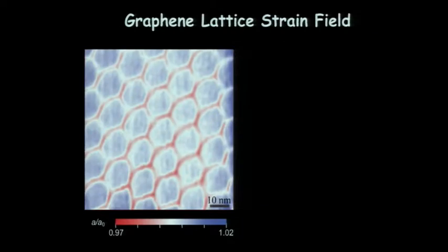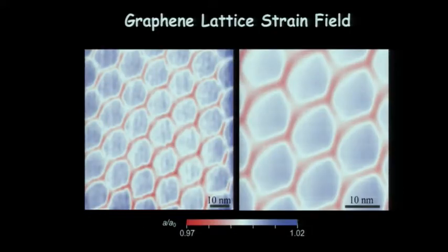And if we take this data now and we just look at 1 unit cell and take a little higher resolution, what you see here is that in the center of the unit cell, the graphene lattice is expanded. So it's 1.02. That means that the graphene is matching the boron nitride in the center there. And then it has to relax along the edges of these domain walls to keep the overall lattice constant fixed, the overall area of the sample fixed. So we're stretching in the center and relaxing along the outside. Sorry, Brian, this was under which imaging condition? The one where you're pushing strongly? This one is the middle imaging condition.